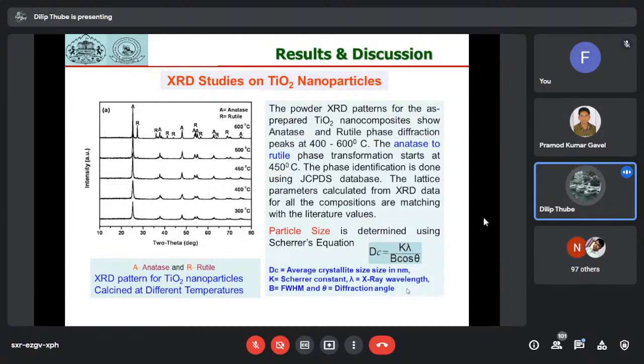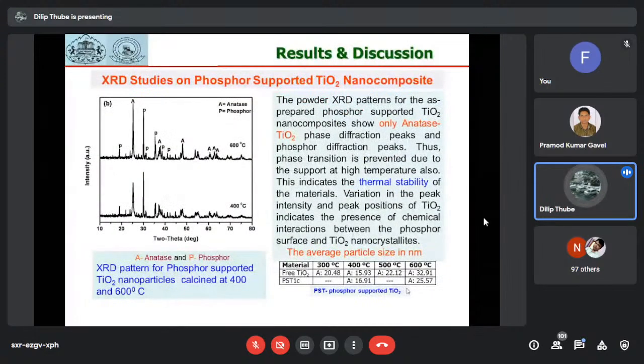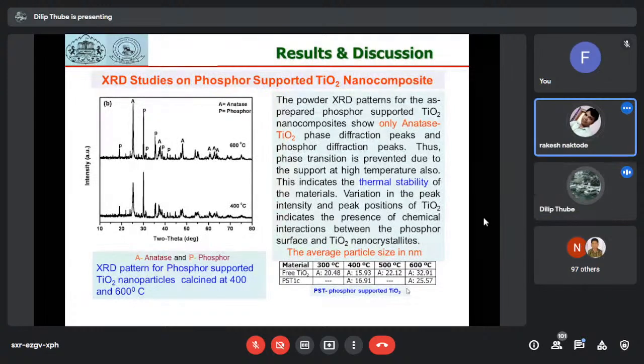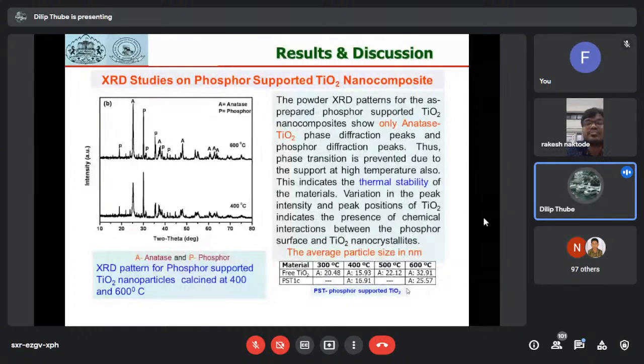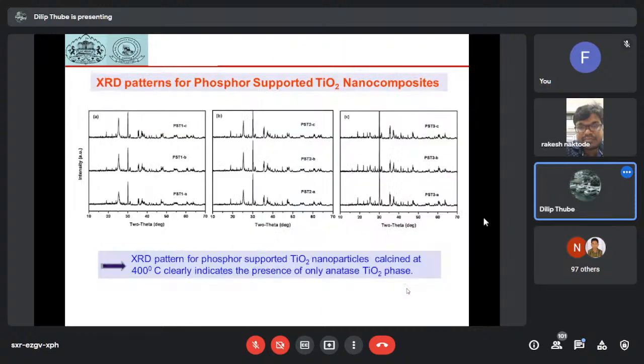there is a rutile phase which is crystallized at about 600 degrees Celsius, whereas for phosphor supported nano TiO2 material, at 400 degrees Celsius there is no rutile phase, as well as at 600 degrees Celsius, there is no rutile phase. Rutile phase starts beyond 750 degrees Celsius in these materials. So we have optimized the sintering temperature in these materials, right?